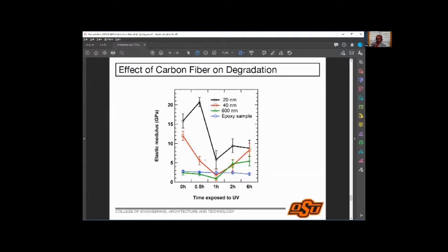So in an actual composite, it's very difficult to study UV degradation, because UV degradation occurs only in the top 3 or 4 microns, and it takes very long hours of duration to observe anything. So for example, here we are looking at only 6 hours of duration, because the changes that are occurring in the material are only occurring in a very thin surface. But because we are using AFM based indentation, that is enough for us, because we don't care about what is going on underneath.